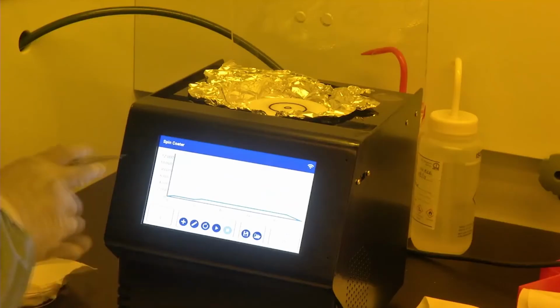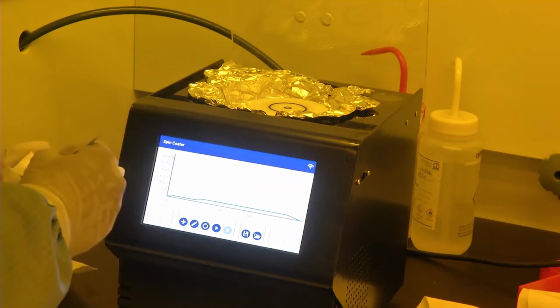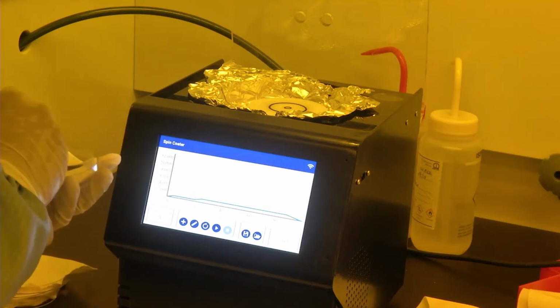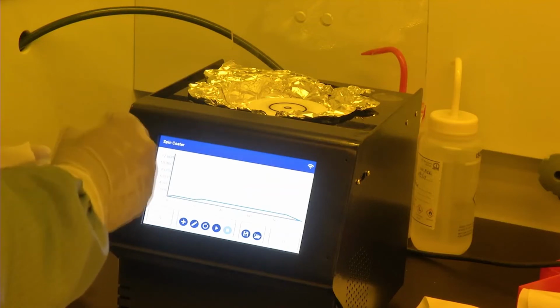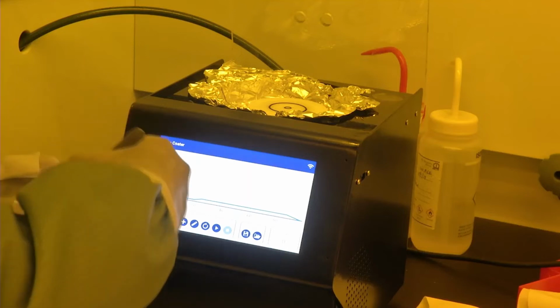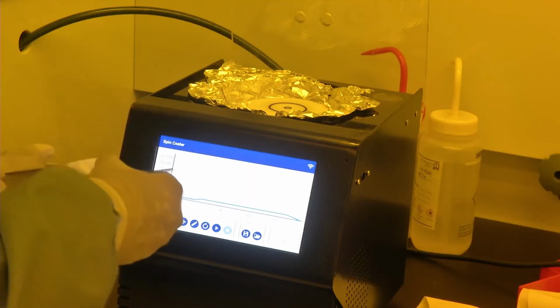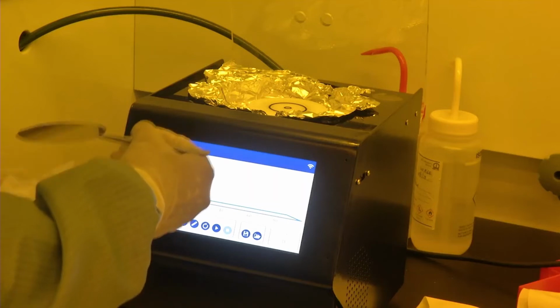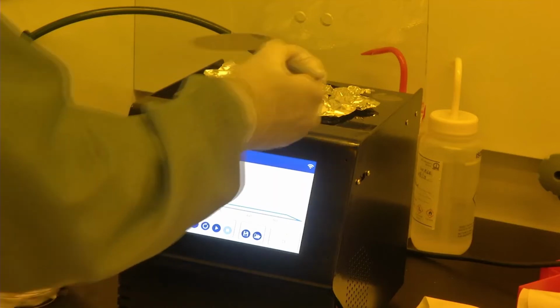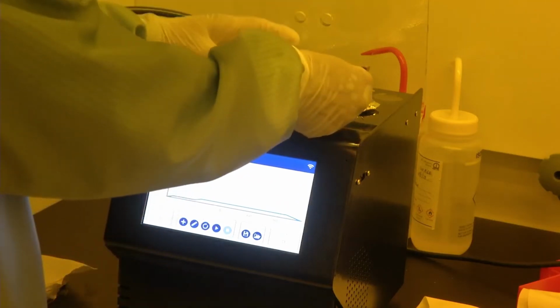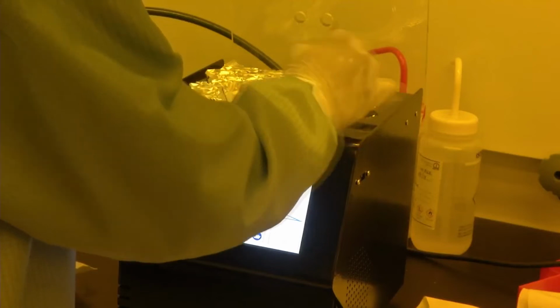So now we will see how the precursor of the polymer can be spin coated onto a carrier silicon wafer. My colleague is showing how to place the silicon wafer. We need to be very careful. We will place the polished surface facing us and the non-polished surface down, in case of a single side polished silicon wafer.